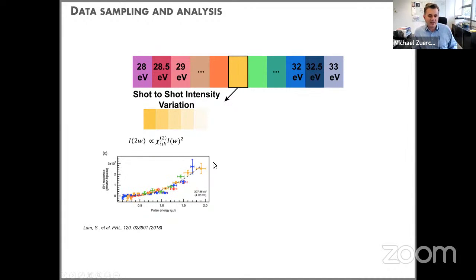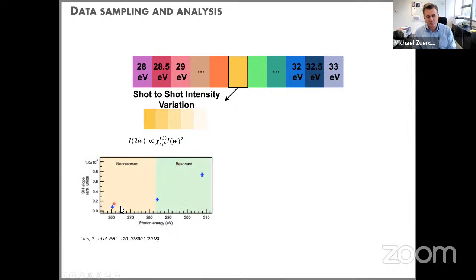So we automatically sample along this curve. So the measurement becomes a matter of statistics. Yeah, and that is actually great. So a bug becomes a feature in this case, and we can essentially directly create such a curve just by collecting data for a while. So we use the shot-to-shot intensity variations to actually map out pulse energy over roughly a factor of 2, 3, 4, up to an order of magnitude, to actually get a very nice fit for Chi2 extraction. And that was what was done in this first reported experiment.